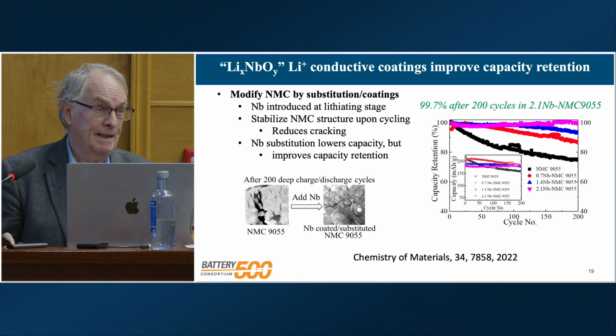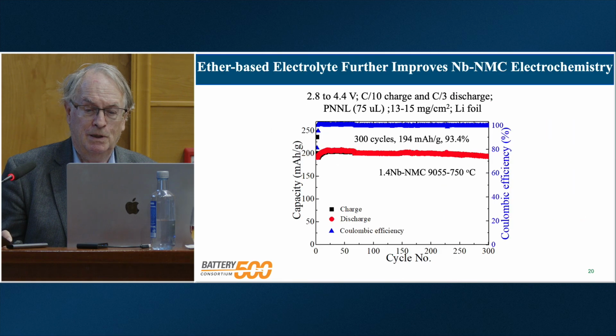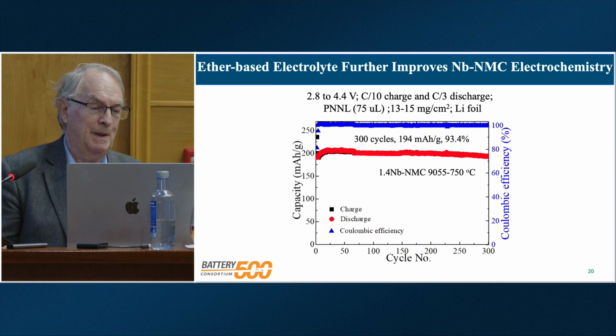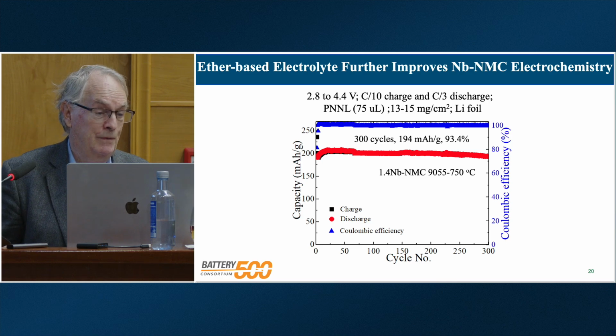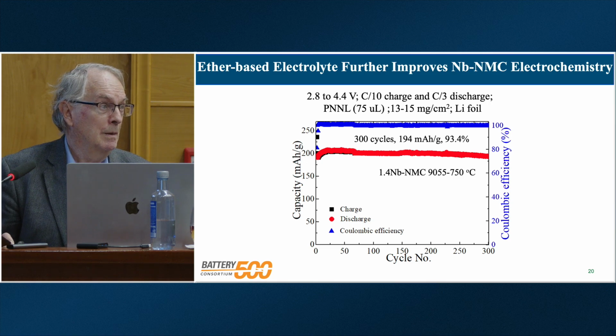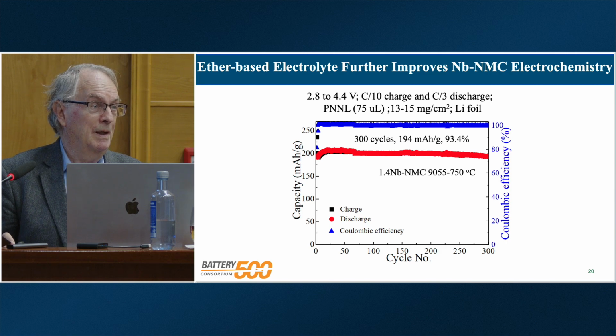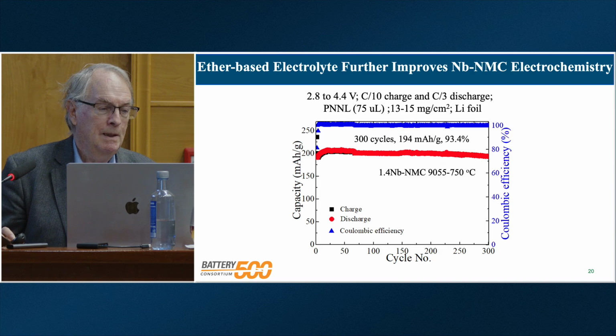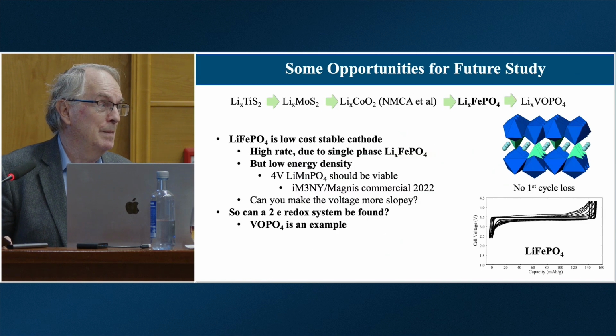LiPF6 organic carbonate electrolyte. It turns out if we switch now to an ether-based electrolyte, you can see we've got 100% coulombic efficiency, and we've got no capacity loss essentially over the first 300 cycles. So we're researching both the material itself and the electrolyte we're working with. Let's switch away from the NMCs for a moment.